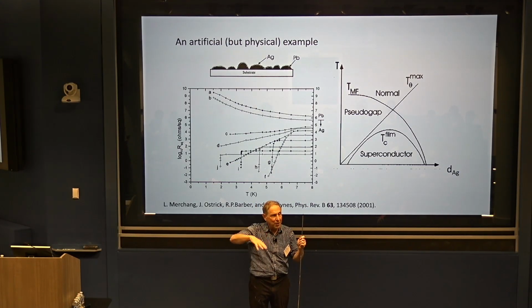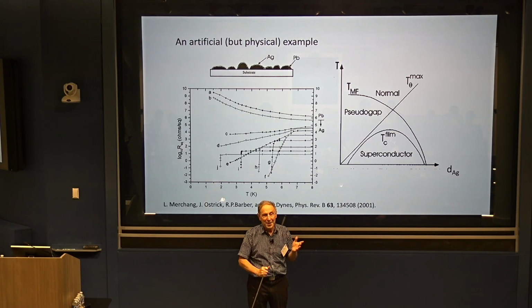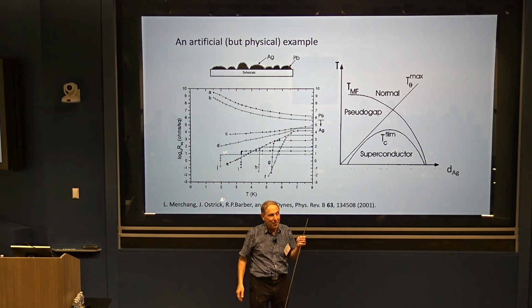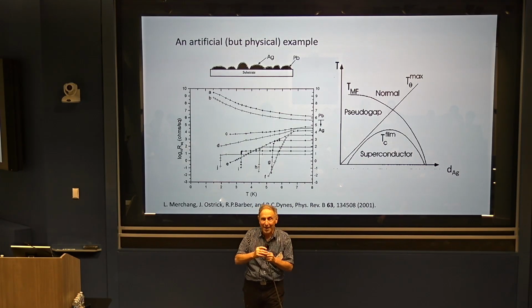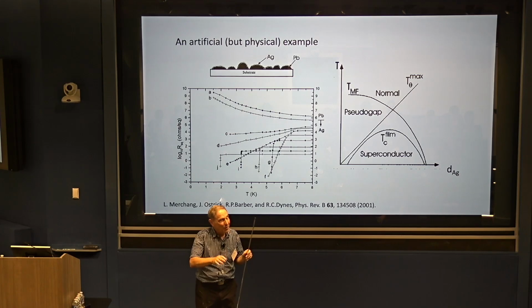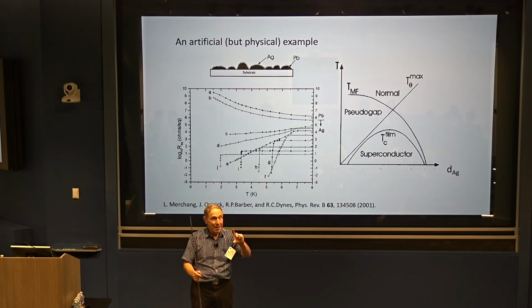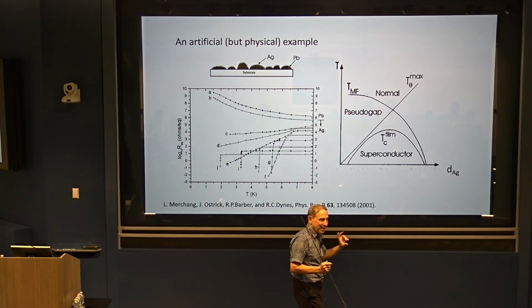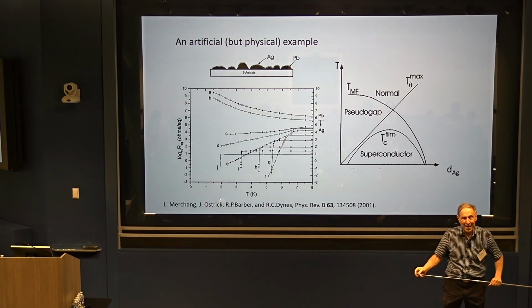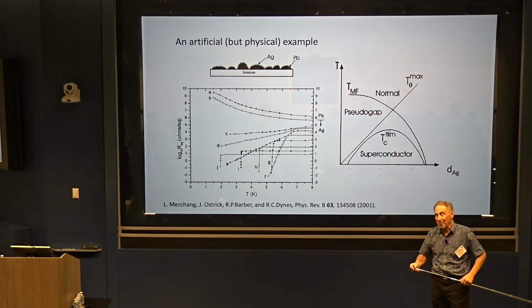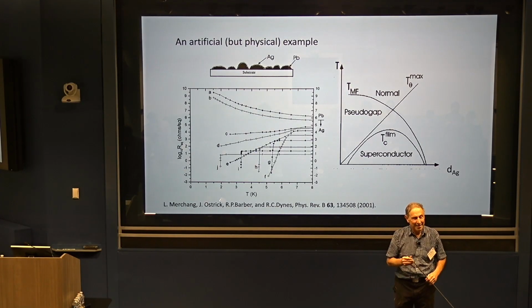These photo-induced superconductivity states in YBCO, half of the people I talk to say aren't light-induced superconductivity and half say they are. So let's put that on hold for a second. But what they have done is drive the apical oxygen up and down. And what you can see is if you look at that from this bilayer, when the oxygens go like this, this layer gets more doped and this layer gets less doped. So they are oscillating precisely the asymmetry that I think is a potential big lever. So, okay, I can take optimism from that. There's nothing on the trilayer of this.